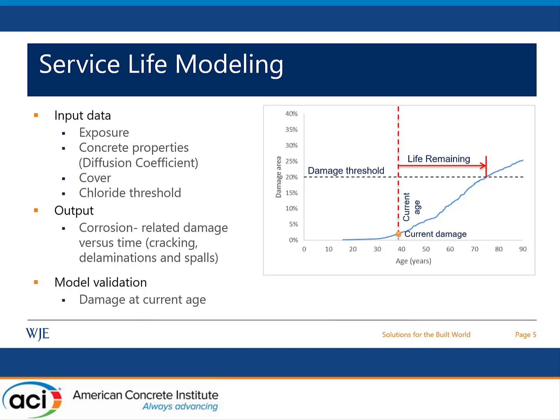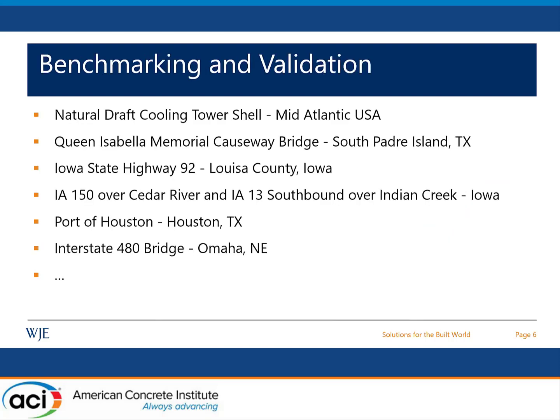And the output of our analysis would be the percentage of corrosion-related damage with time. And based on the damage threshold or the service life criterion, we can estimate the remaining service life. And then we validate our results based on the percentage of damage at current age that we estimate based on the field investigation.